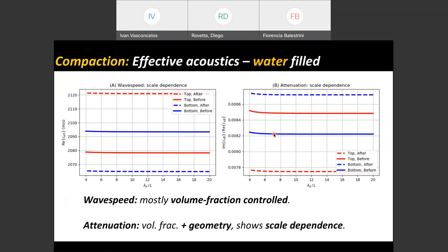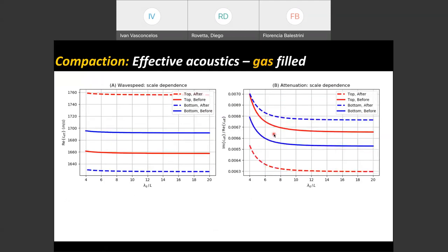But what happens if we're doing, for example, a CO2 sequestration experiment, and this water is replaced by gas? So we're going to replace water by gas. These plots are going to change. So this is with water, gas. Notice on the left-hand side first that the overall picture didn't change very much. So the top wave speed increased, the bottom wave speed decreased. It mostly doesn't depend on frequency. The only thing that's happened here is that the absolute values have changed, because when we fill with gas, the pores are more compliant than before, so the overall effective wave speed is slower. That's the only thing that's different from before.